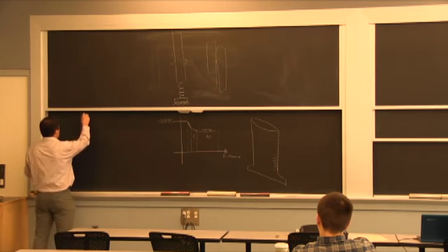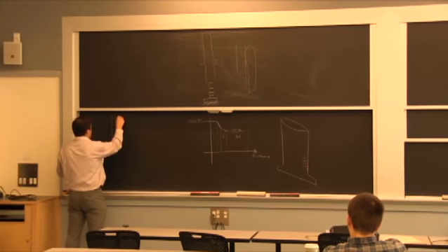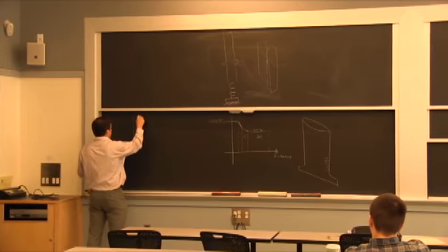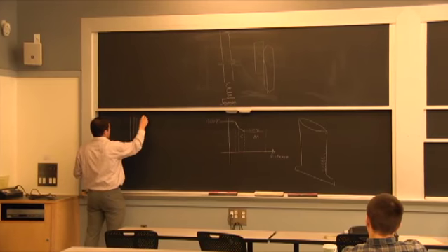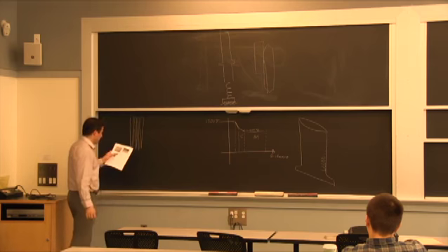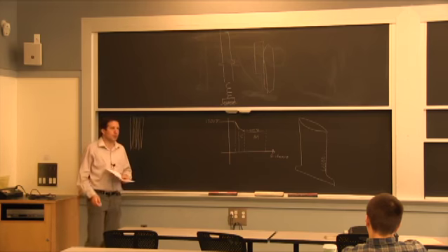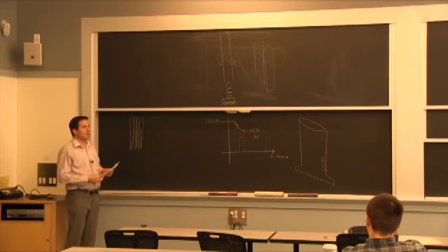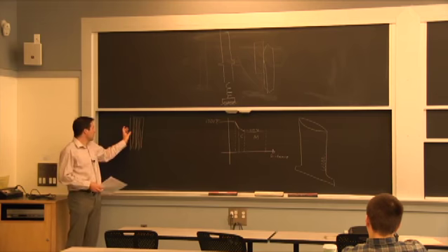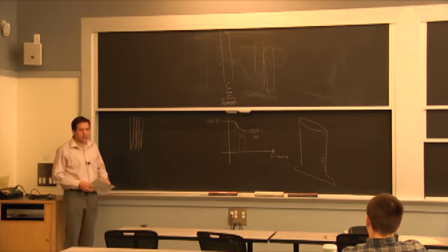It's very columnar, and it's also very loose between them. It's not that different from an anodized layer that you have on aluminum. So porous, columnar. This coating will be able to withstand a differential in thermal expansion.